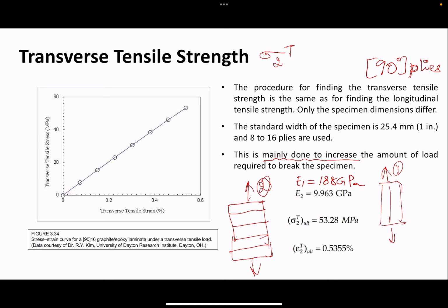In direction 1, the Young's modulus was 188 gigapascals. Direction 2, it's less than 10 gigapascals. Similarly, the stress and strain values are also very, very low. So you always try to make sure that when you design something in composites, the load on it is mainly in the direction of the fibers.